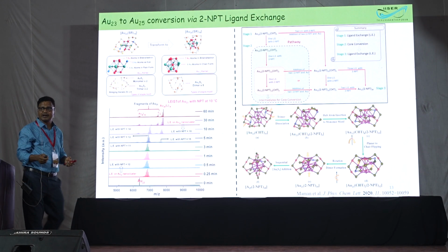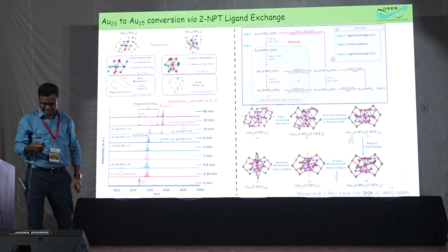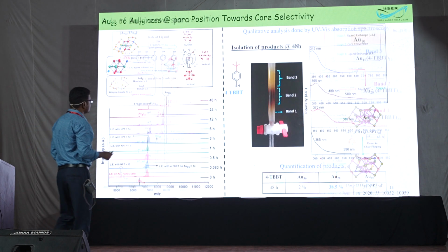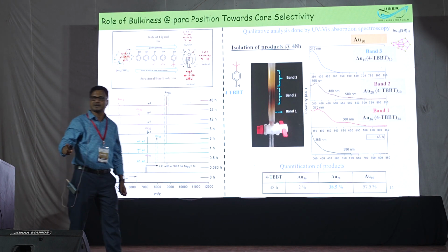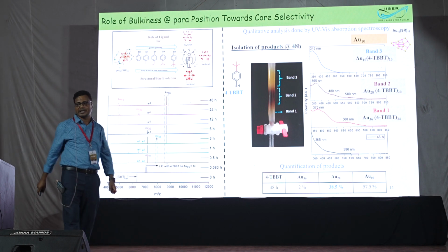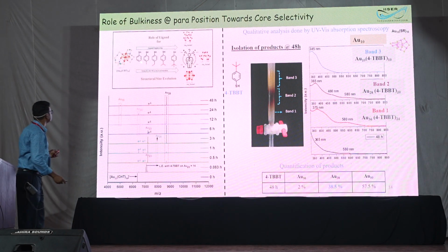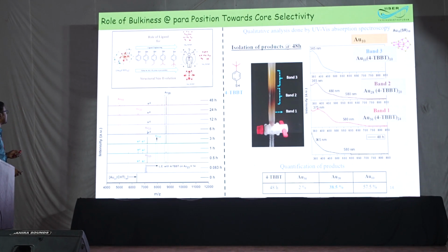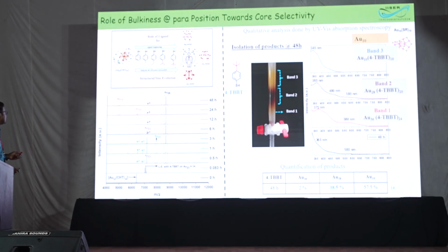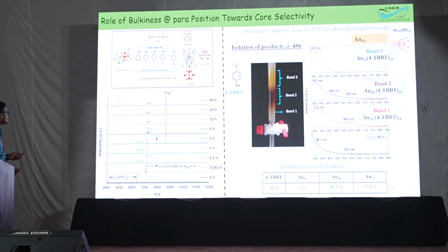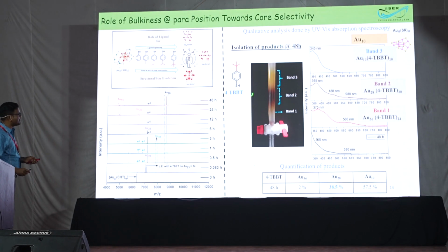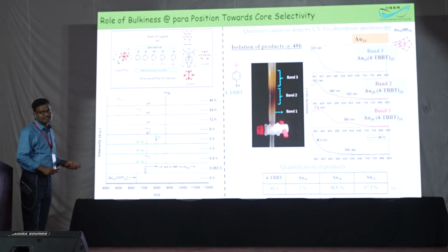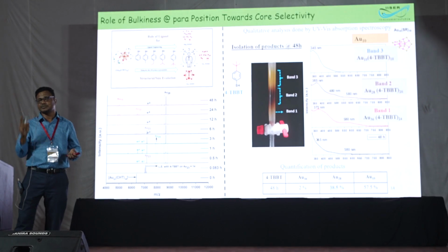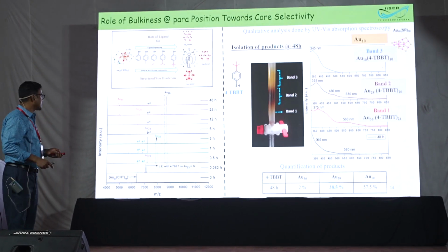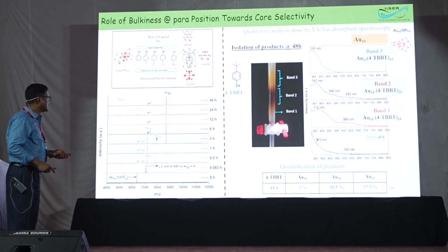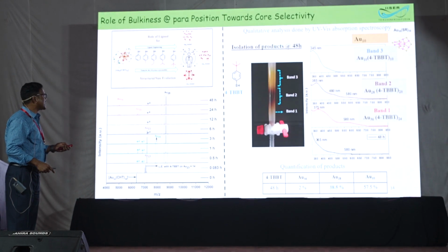So we have benzene thiol, and we have tertiary butyl benzene thiol. We thought that with benzene thiol we get the Au25 cluster, and with tertiary butyl we get the Au28 cluster. Then we did a sequence of reactions. This is the benzene thiol. We sequentially added methyl, ethyl, isobutyl, and tertiary butyl. In every case, I have mentioned that we have different products and analyzed them. In every case we did the mechanism like the previous cases. We can see that we are getting Au36, Au28, and the byproduct.